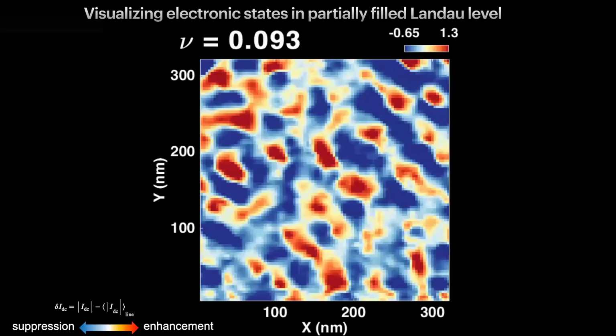I won't bore you with this, because I want to show you, well, that's actually not boring. There's a lot of physics to discuss there, but I just want to show you imaging. So I'm going to tune the STM tip bias to just at the edge of the Coulomb gap, where you're just beginning to put electrons into the sample. And we make an experiment where we plot in real space how much current is going into the sample without actually measuring conductivity. We're just measuring current. And this experiment is done with open feedback loop, meaning you're not adjusting the height of the tip, so it makes it kind of more exciting, dangerous because you could crash. But you can do it if you have a very stable instrument.